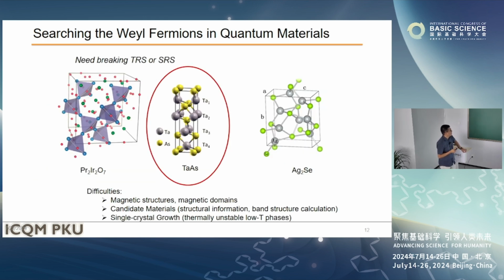Okay, so how can we find the Weyl fermion or Weyl node in quantum materials? You need either to break time reversal symmetry, meaning you need magnetic materials, or to break inversion symmetry, meaning you have some compound with a slightly strange crystal structure. So in 2007, actually, the initial prediction was a pyrochlore compound, the iridate. But this compound is magnetic and has a very complicated magnetic domain problem. So until now, people haven't confirmed experimentally that it is a Weyl semimetal. And other people made some suggestions for candidates, like tantalum arsenide, silver selenide.